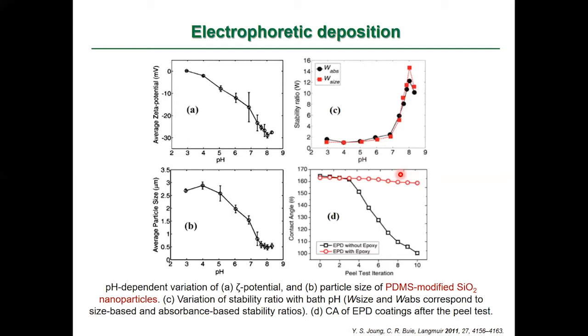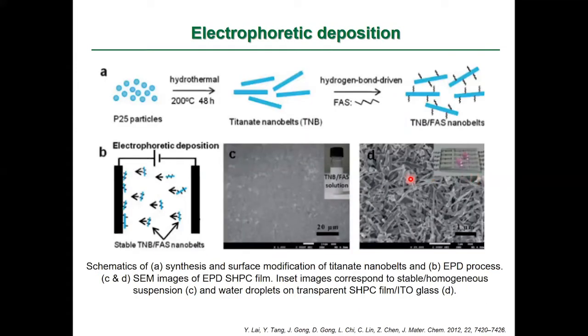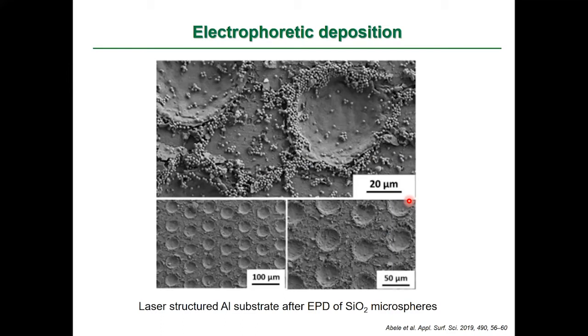So there are different approaches you can use to enhance durability of superhydrophobic surfaces. This is another example where they made titanate nanobelts and then subsequently modified them with fluorosilane and subjected them to electrophoretic deposition. You can see the solution and the surface like this. In another example, see the laser structured aluminum substrate. You can see the laser domes, and on the surface, the EPD SiO2 was coated. You can see the small particles. In effect, it makes a nano micro scale hierarchical surface structuring. For example, in the case of a biomedical implant, it can yield additional bioactivity, and it has several applications.